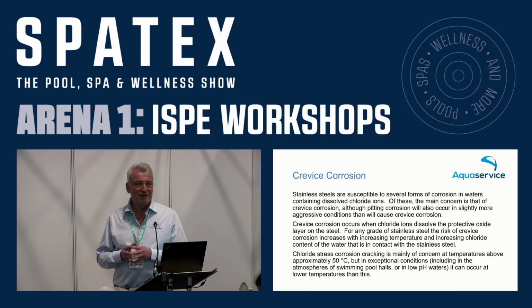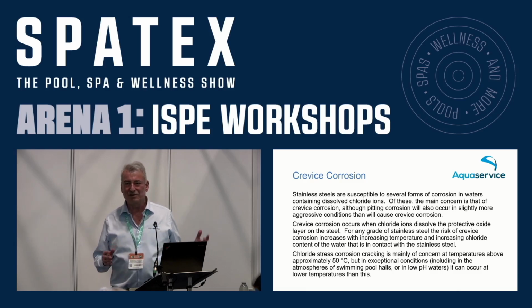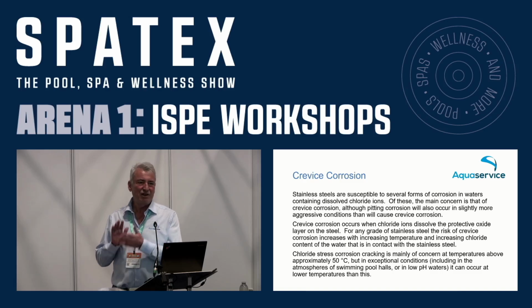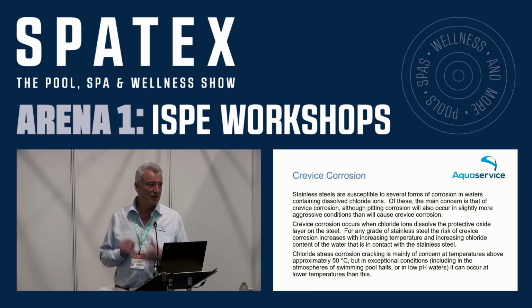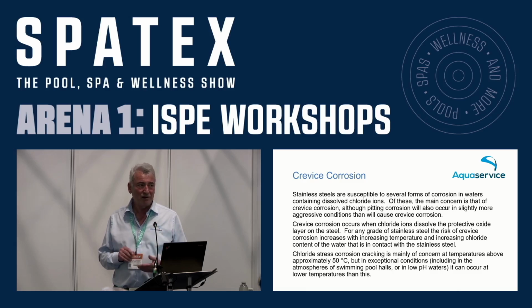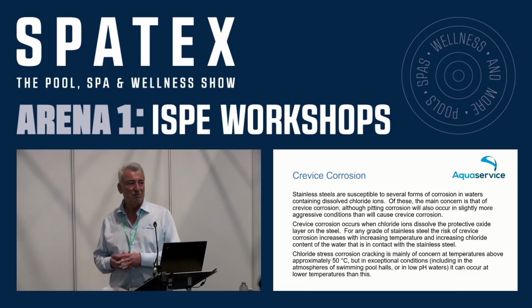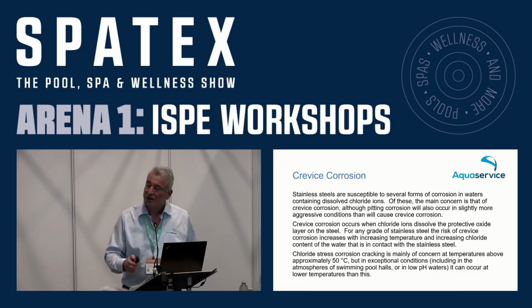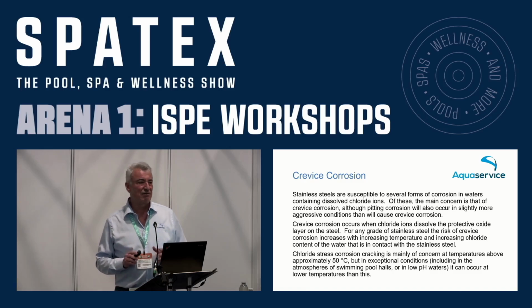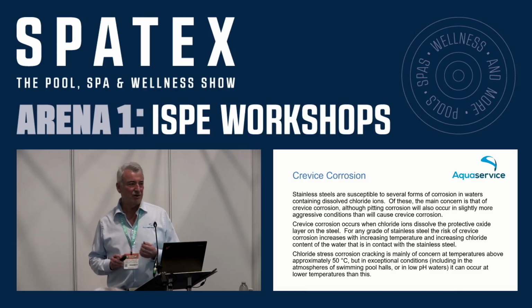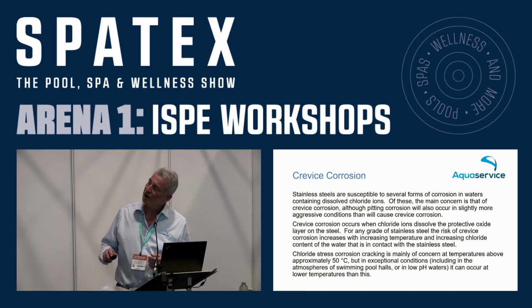This is quite more serious than that surface corrosion, because these crevices occur on a UV chamber between, say, a flange and the body of the chamber, or any clamps that would attach instruments like UV intensity sensors and temperature sensors. It can also occur on welds and also beneath dirt particles. The effect of this corrosion, I mentioned chloride, that's the aggressive agent, but it's also very much influenced by the water temperature. But I will show you a few examples.